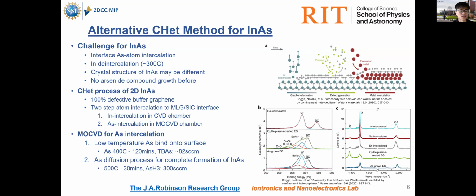And to get a better result, our new alternative CHet method is that we decided to use 100% defective buffer graphene. So we only keep the bottom buffer graphene layer for intercalation. So it gives us a higher chance to introduce the arsenic atoms. And we are also using a two-step annealing process when we grow the arsenic atoms.